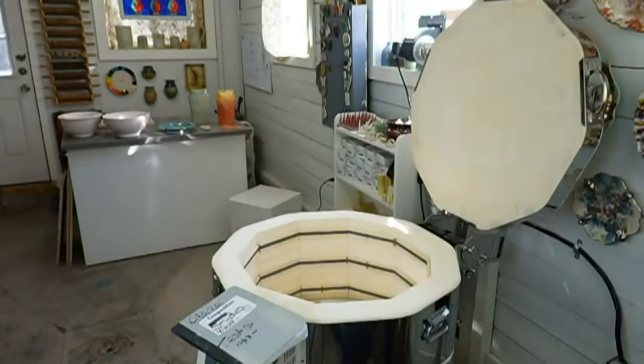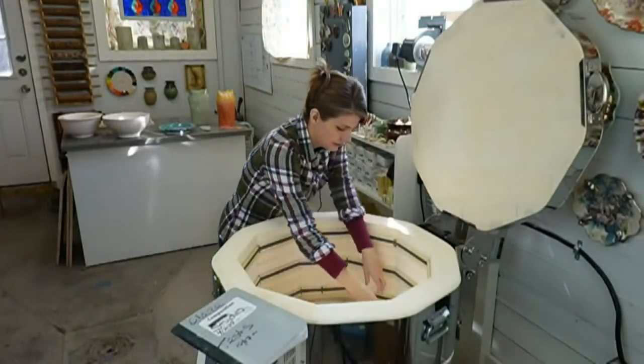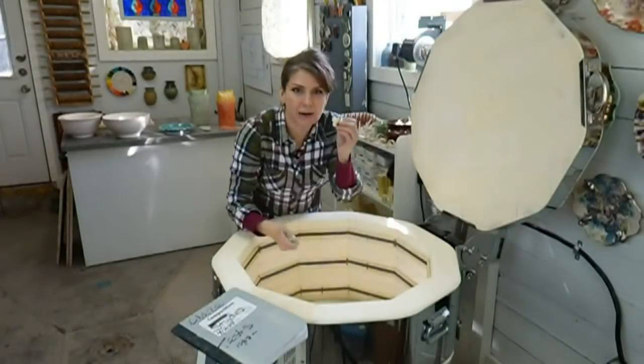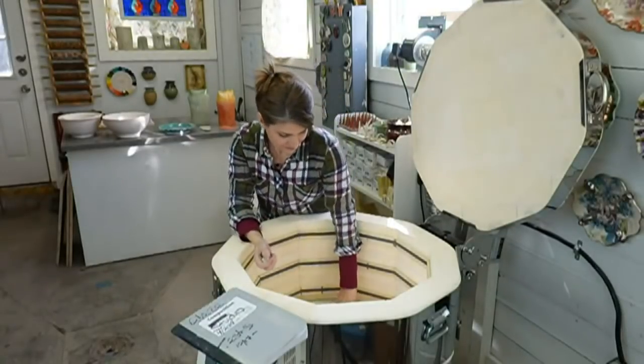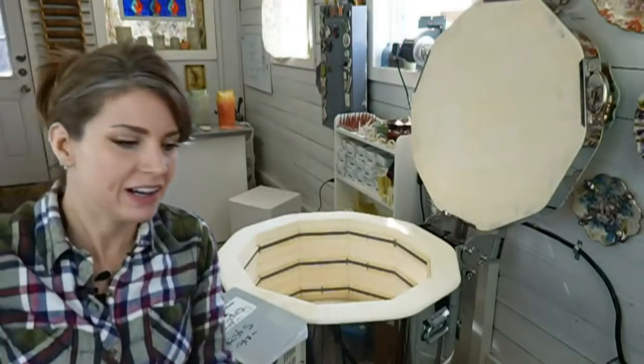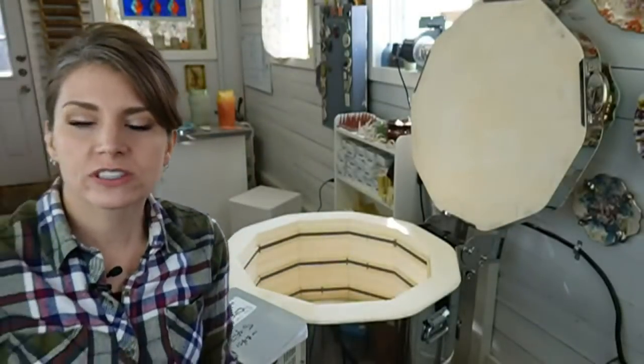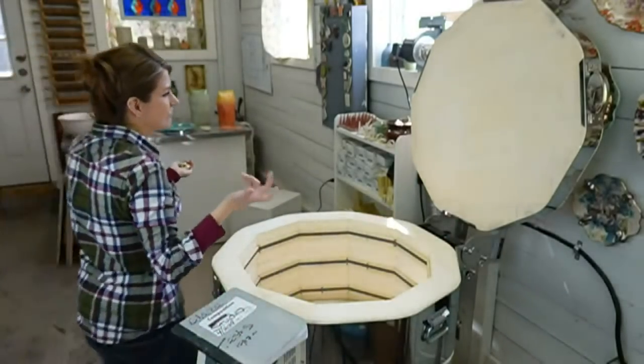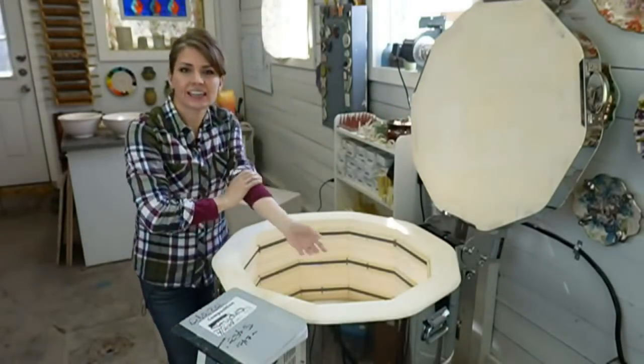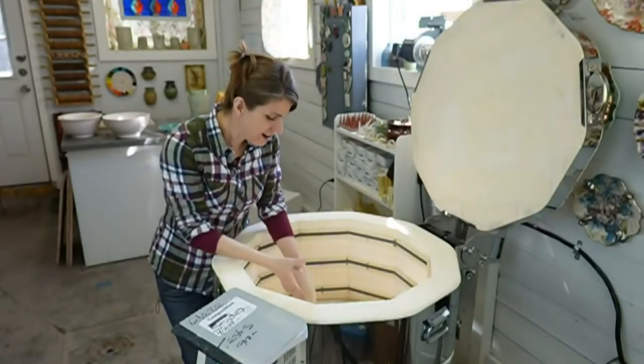Ceramic Shop has them. Okay, so Teresa's sharing those. And I've got a few more. Usually I just tap them on my kiln shelf. Tap, tap, tap. And I have a bucket of them by my kiln. So that way I don't lose them, I just keep track of them. Can you reuse the stilts? Of course, yeah. I've been using some of these for over 10 years. They're made with nichrome wire and in a ceramic support. So as long as the nichrome wire doesn't wear off, you'll be fine.